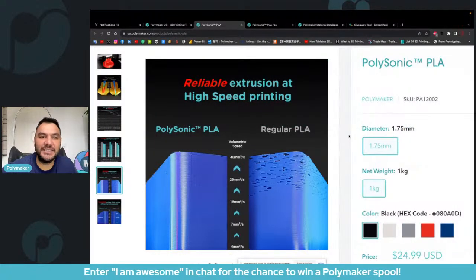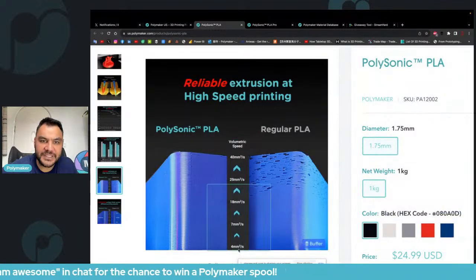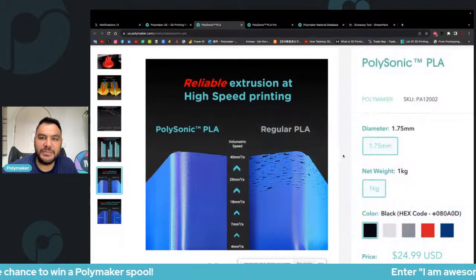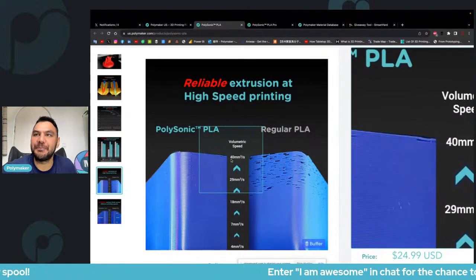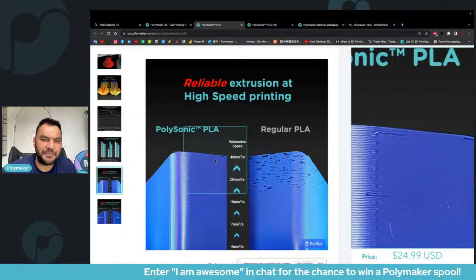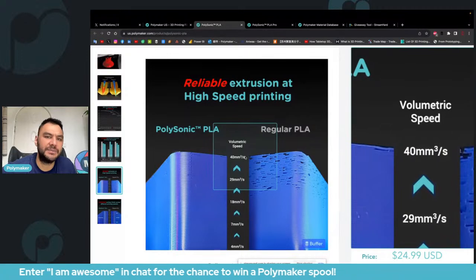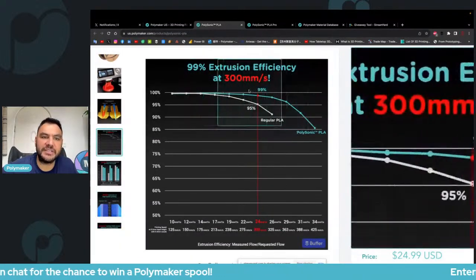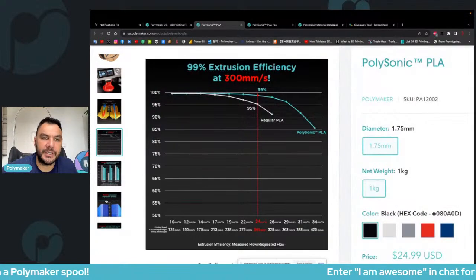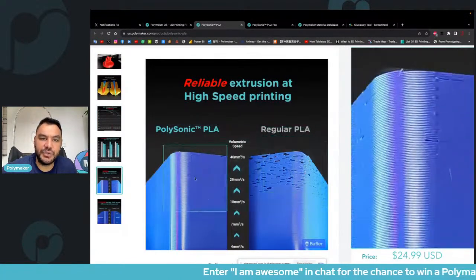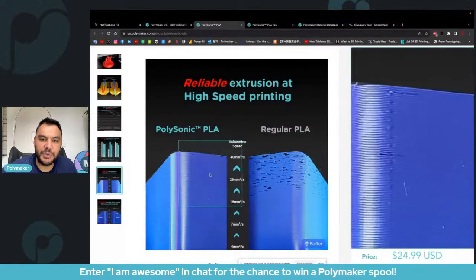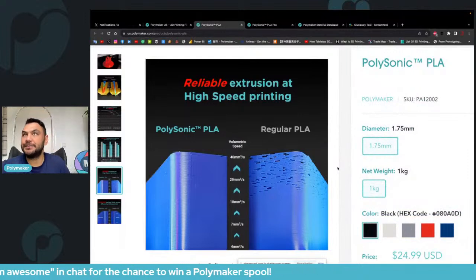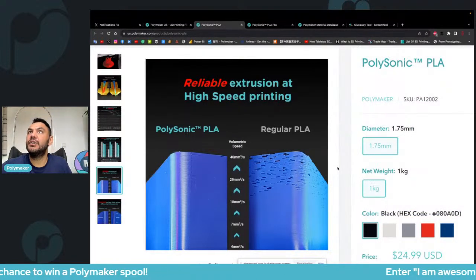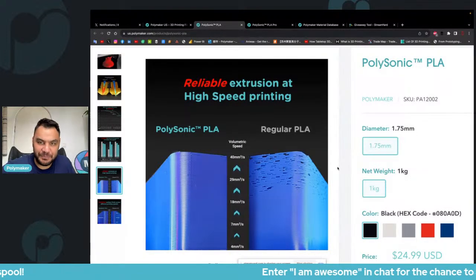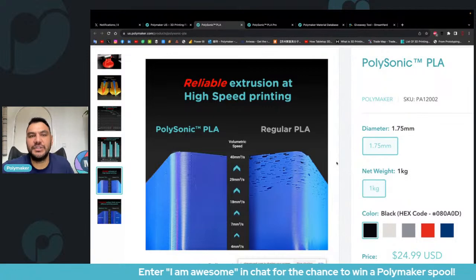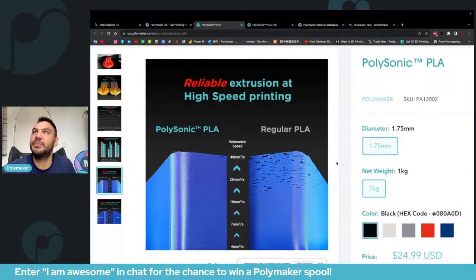Anyway, so reliable extrusion at high-speed printing, polysonic PLA. For this test, it went pretty far. I think it's Zombie that made this test. He went up to 40 millimeter cube per second, but I think it was a CHT nozzle, and I think it was a 0.5 or something like this. So not to compare with this, because the setup was different, but it's just to show you the difference between the polysonic PLA and regular PLA. Speed is nice and all, but when is the reinforced ABS ASA coming out? Soonish. I mean, you still have to wait more than half a year, but soonish.